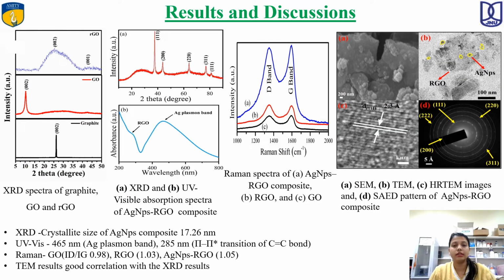So coming to the results and discussion, the synthesis of the silver nanoparticle reduced graphene oxide composite was verified using XRD, UV, Raman, and the scanning electron microscope as well as TEM. These results show that they have been synthesized, and from the SEM and the TEM image you can see that the silver nanoparticles are spherical in shape and they are highly agglomerated.